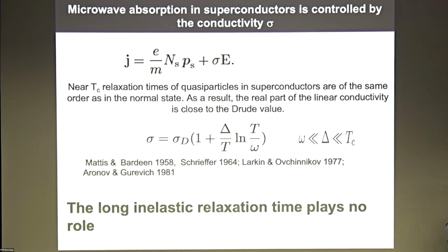The message here is that if you measure microwave absorption in s-wave superconductors, it is always smaller than or of the order of that in a normal metal. Near Tc, quasi-particles behave roughly like in a normal metal. If you go down in temperature, microwave absorption decreases. Also, this is through the conductivity, so microwave absorption is controlled again by the elastic relaxation rate. Our goal with Anton is to go from one effect to another in a superconductor and substitute the elastic relaxation time with an inelastic one, which means many orders of magnitude.